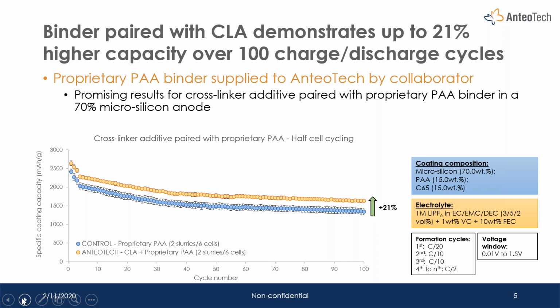And what we found is that by pairing these two components, we are able to achieve up to 9% higher starting capacity of the silicon anode and up to 20%, 21% actually, higher capacity at cycle 100, which was a very good result. We also used a very difficult test system for this approach, containing 70% microsilicon. And what this does is it expands a lot, up to 300%, placing a lot of stress on this anode coating and the anode as a whole, which is exactly what you want when you want to evaluate new and advanced binder systems. And we were able to create this beautiful result.